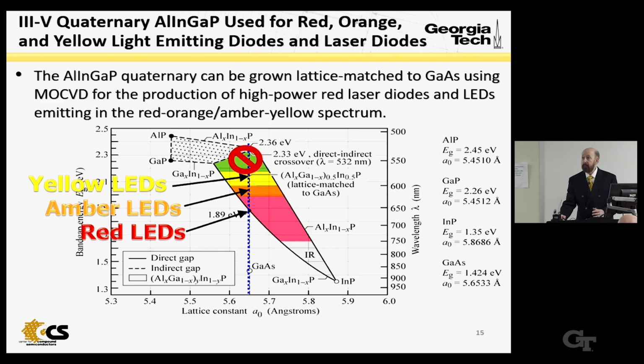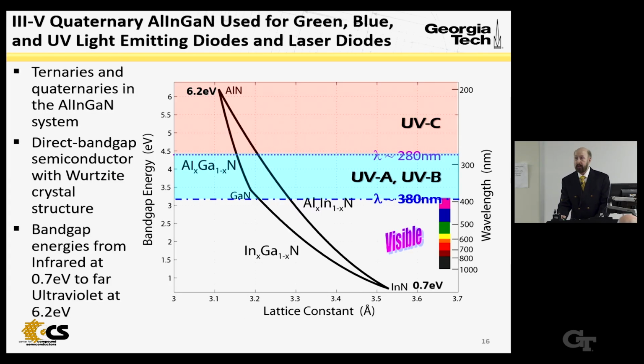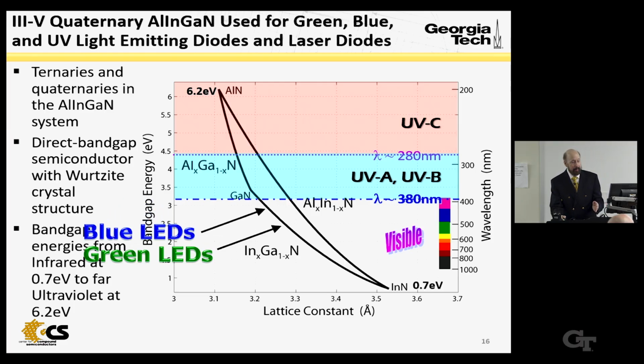So we have to find another solution for green, blue, and UV LEDs, and that solution is the quaternary aluminum indium gallium nitride. Again, band gap energy versus lattice constant. In this case, it's a Wurtzite crystal, so this is the A-plane lattice constant. And as you can see, there's no good way to make a lattice-matched green LED because we don't have a substrate of indium gallium nitride yet, although Alan's working on that, I think. He has, at least. At any rate, so you can grow these materials on sapphire, which Hal Manasevit was the first person to do, by the way.